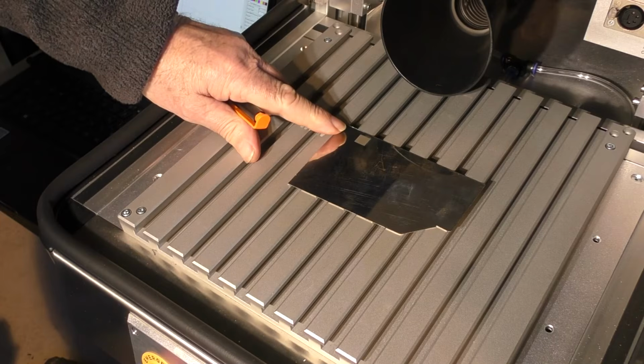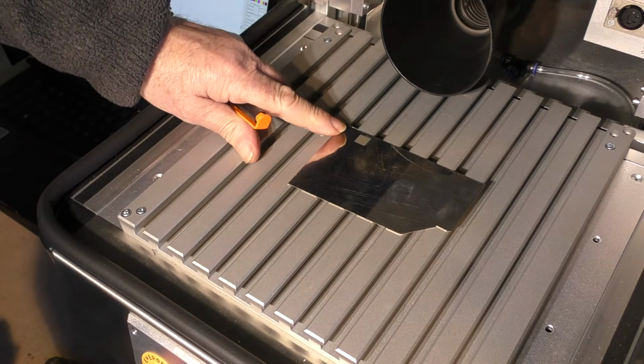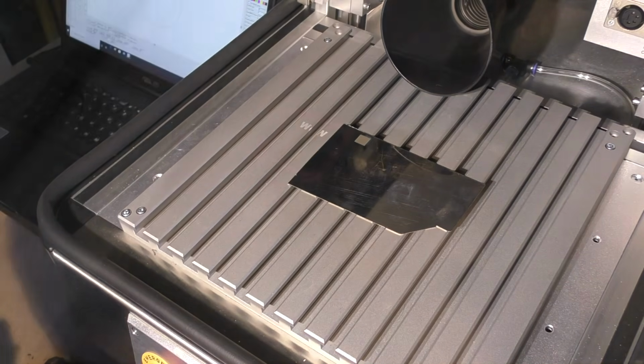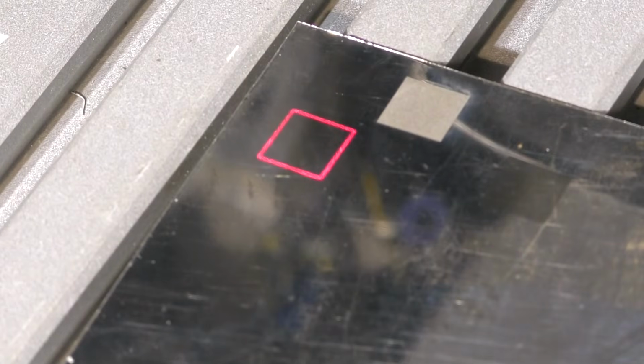Because as we slow the speed, we get more pulses per millimeter, and that means we're going to do more damage by running slower. Here's the first one that you can't see, which is 2000 millimeters a second with a 2 nanosecond pulse. Okay, so now we've reduced the speed to 500. So it's a quarter of what it was before at 2000.